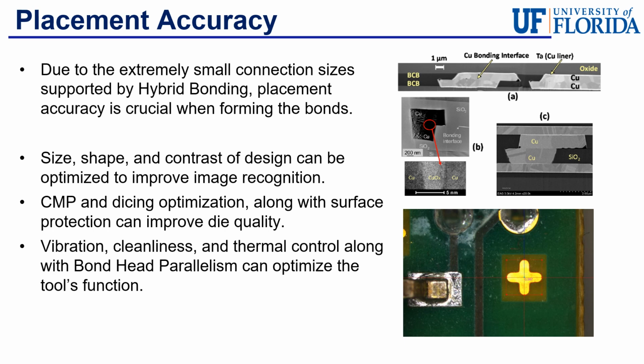One final consideration is the placement accuracy of the two components when they're brought together during the hybrid bonding process. Due to the extremely small pitch sizes that are supported by hybrid bonding, the placement accuracy is exceptionally crucial when forming these bonds. Taking a look at this cross-sectional image, if the wafers are misaligned by as little as a few micrometers, it can cause connections to be misaligned, improperly connected, doubly connected, or bonded to completely different connection sites than initially intended. And this would cause the whole bonding process to be a failure, making the wafer useless.